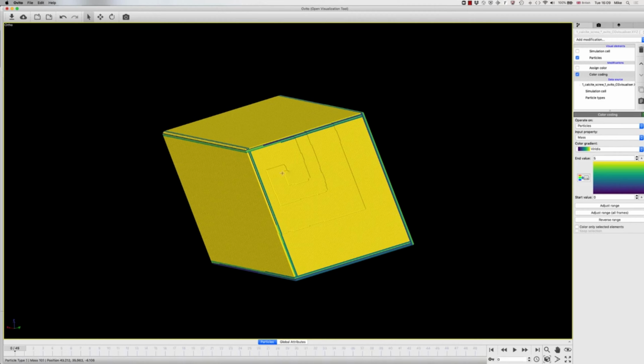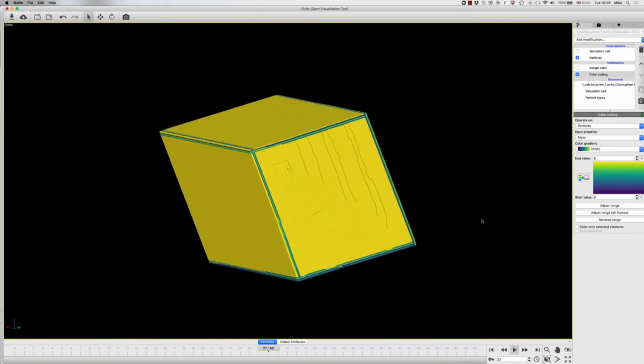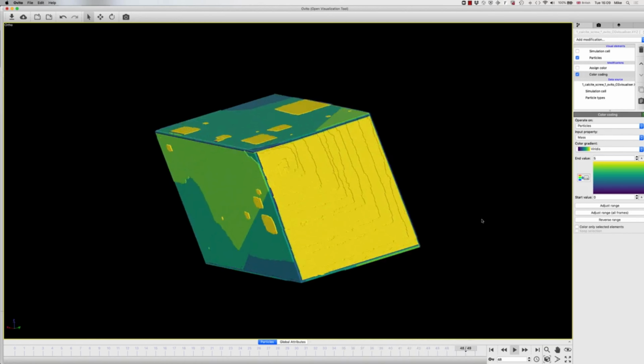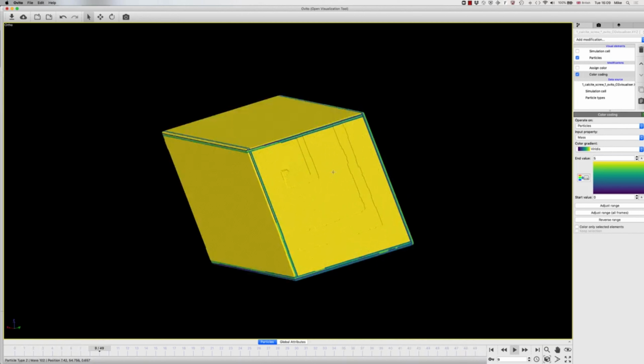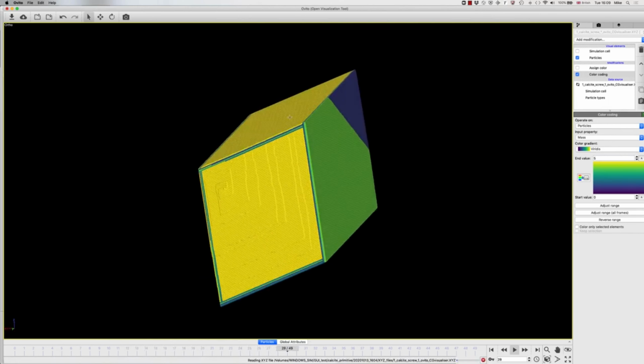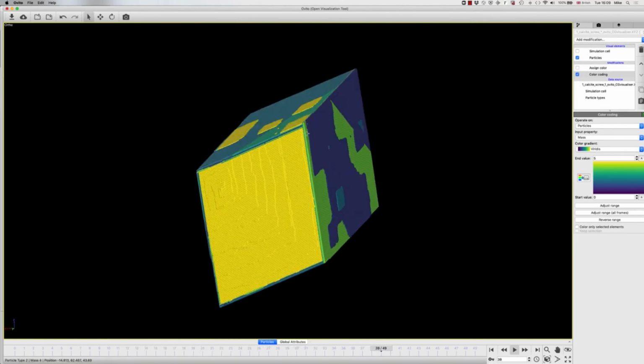okay, so now we can see at the beginning of the simulation we don't have that problem because we've allowed it to heal for 1 million at the beginning. Now we're running at 1 kilocalorie, and then we move to 2 kilocalories, and then finally we move to 4 kilocalories, and we can see when we get to 4 kilocalories we actually switch on the layer by layer growth on the side.